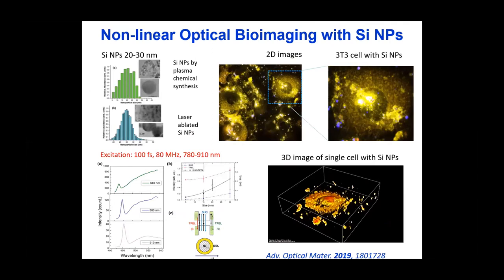Because luminescence is efficient only for very small, highly passivated nanoparticles — which are not easy to prepare and maintain in water — we examined the properties of very large nanoparticles from laser ablation in water, with a mean size of about 20–30 nanometers. We also compared luminescence properties of nanoparticles prepared by plasma chemical synthesis — plasma treatment of silane — which also produced large nanoparticles with typical sizes of about 20 nanometers. They were near single-crystalline, but their sizes were significantly larger than required for visible light emission due to the quantum size effect.